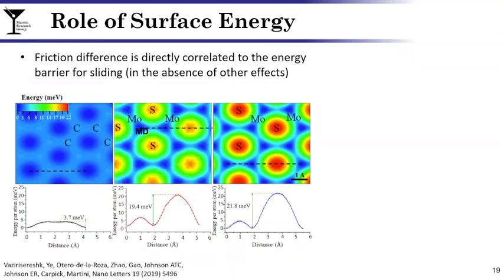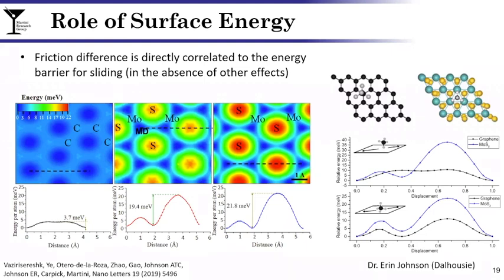Again, this is an empirical model, so we obtained corroboration from density functional theory calculations performed by Erin Johnson's group at Dalhousie. Those are shown over here on the right. And you can see, in this case, the DFT approximated the tip as a methane molecule. And you see 2 different orientations. In both cases, the energy barrier for sliding is higher for MoS2 than graphene.